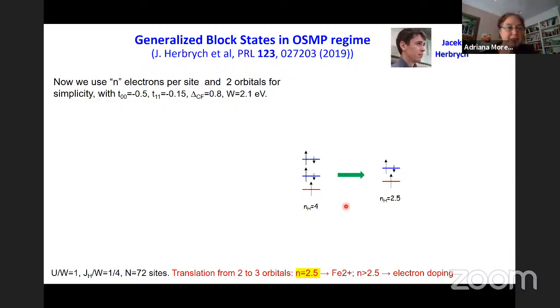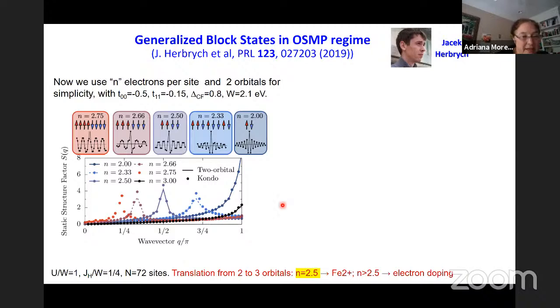We studied the static structure factor. In the limit where we have 2 electrons per site—a little below the 2.5 that would correspond to the parent compound—we have an effective spin 1, and we find it orders antiferromagnetically, with a peak at pi.